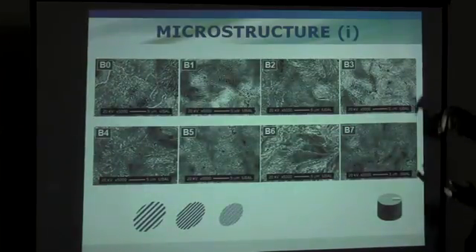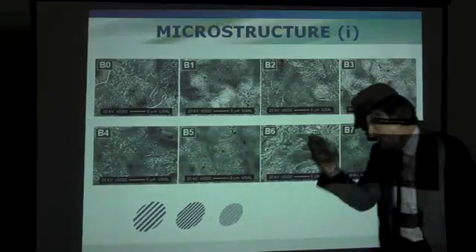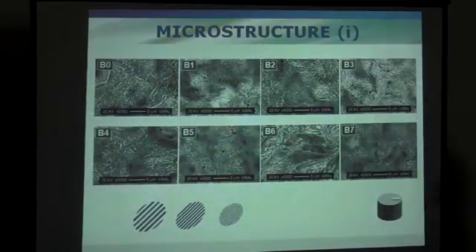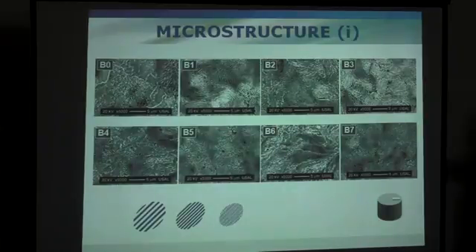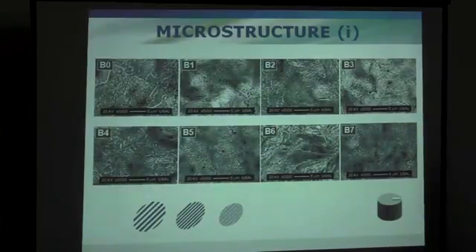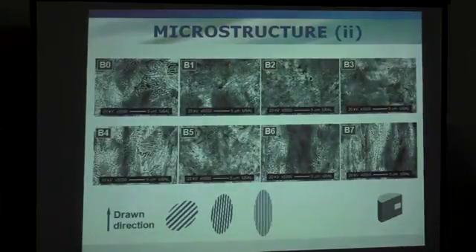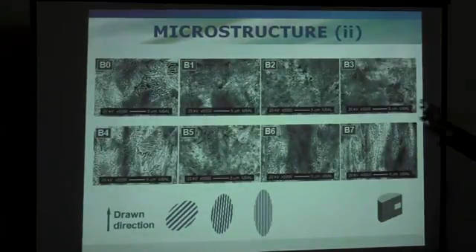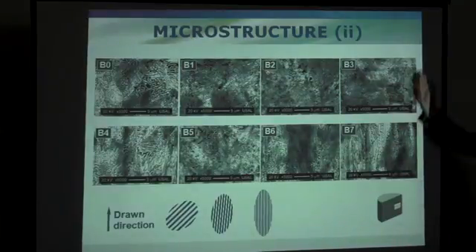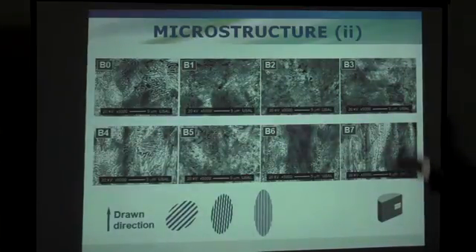Both pearlitic colonies, the set of lamellae equally oriented, and pearlitic lamellae, ferrite cementite lamellae, are randomly oriented in the transverse section. But with regard to the longitudinal section, we have a clear evolution towards a markedly oriented microstructure, a quasi-fiber reinforced material.